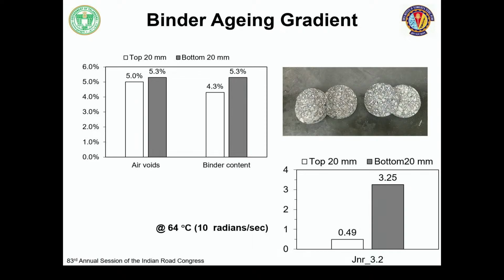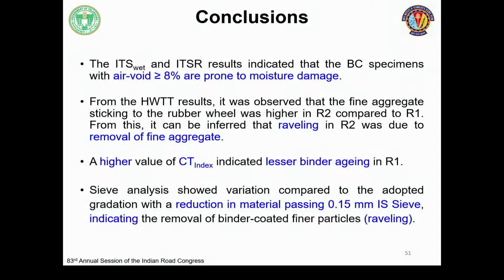And then the binder also became very, very stiff at the surface compared to the bottom. We did the Jnr study and it was shown that it is 0.49 at the surface, whereas it was 3.25 at the bottom layer. It was the same as the fresh bitumen. So here are a few conclusions which I would like to make. When the air voids are more than 8%, the pavement is prone to moisture damage, and that was observed in one of the road sections.